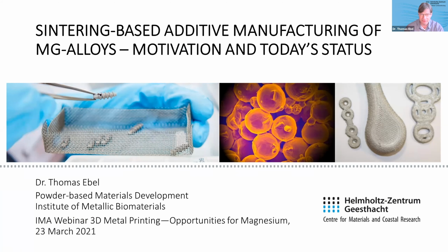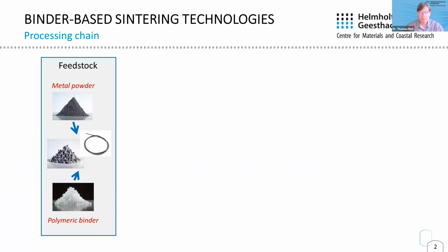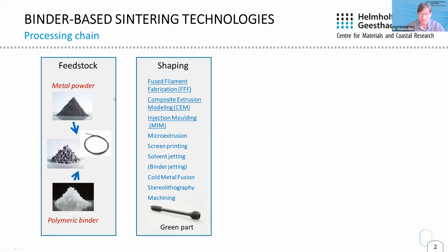I will talk about sintering, and to be more precise, I will talk about binder-based sintering. We heard about binder jetting. That's a little bit different to what I will talk about, because what I mean is that before the shaping process we mix the metal powder with a polymeric binder, so we can get a feedstock like granules or also like filaments or like a slurry or whatever you want. And this feedstock then can be processed by different shaping technologies. Today, there's a number of different techniques, and this list is still increasing. We are using in our institute mainly the first three techniques, and there's fused filament fabrication, which uses filaments, of course, composite extrusion modeling, which uses granules, and these granules are the same we are also using for injection molding.